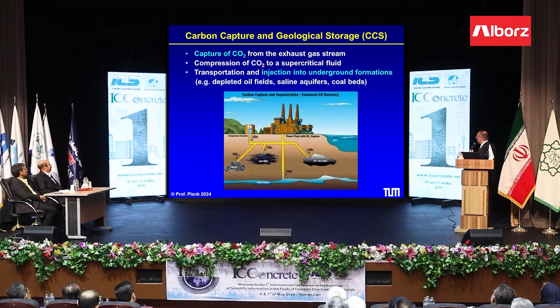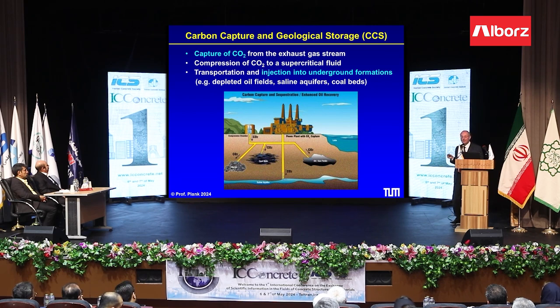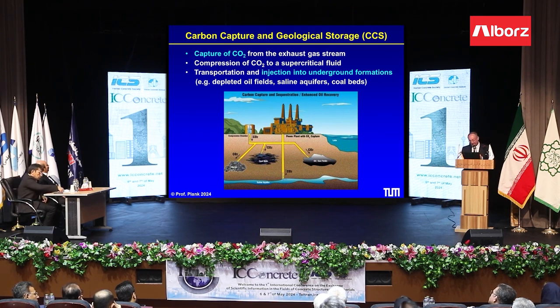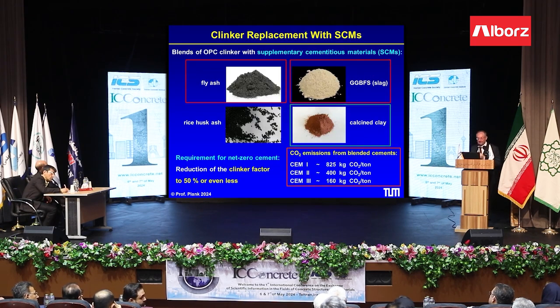What can we do? We can capture the CO2 in the cement plant from the exhaust gas, compress it to a supercritical fluid, and then transport it, let's say, to oil fields and inject it into depleted oil fields. This we call CCS, carbon capture and storage. It's a good way to dispose of CO2, but very expensive. It's already done in the North Sea, so we know the cost. The cost is about 80 euros per ton of cement, and this cost will be added to cement, so this will make cement very expensive.